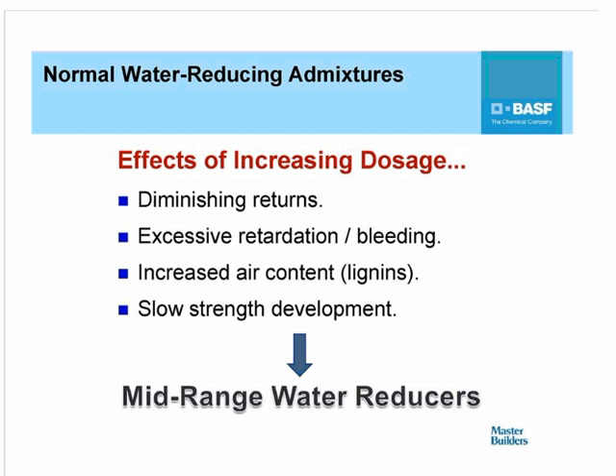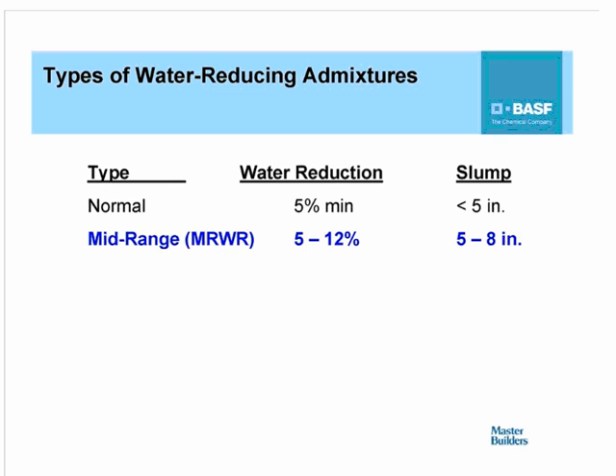And this was one of the reasons why the mid-range water-reducing admixtures were developed. Now, the mid-range water-reducing admixtures, even though there's no specification, typically provide water reduction between that which we get with normal water reducers and what we get with high-range water reducers. So, in effect, they provide water reduction between 5 and 12%. And they work extremely well in the mid-range slump of about 5 to 8 inches.